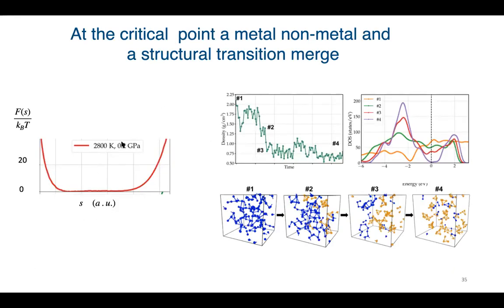It is very interesting to look at the transition at the critical point, where the free energy, of course, is flat. The system can undergo very large fluctuations from high density to low density, and at the same time, the electronic structure changes. In high density, at the Fermi surface, there is a high density of states. Then when I go to the low density, the density of states is zero. So it goes from metallic to insulator.